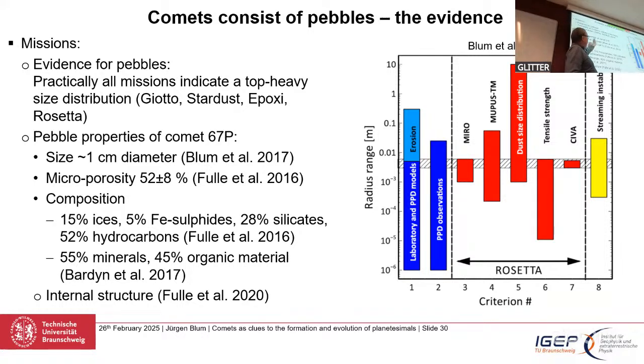They seem to have a microporosity of 50%, plus or minus 10%, give or take. That will play a little role a little later. People have tried to measure their composition. So Fulle and co-workers argue they have little ice, and the refractories consist of 5% of sulfides, about a third silicates, and 50% of hydrocarbons.